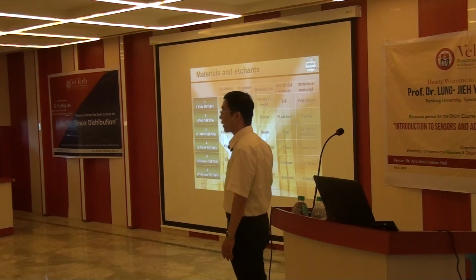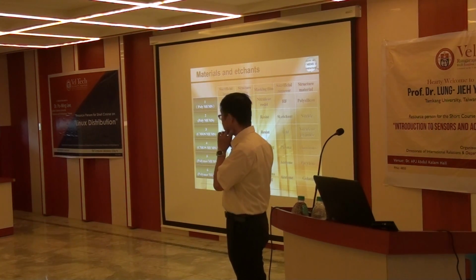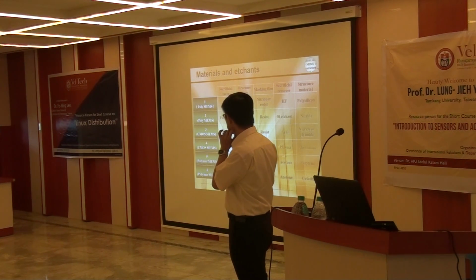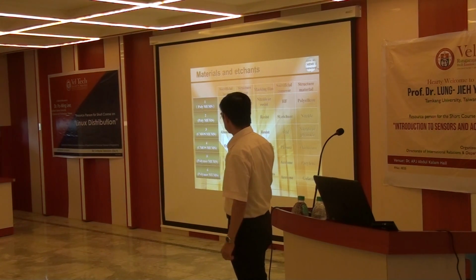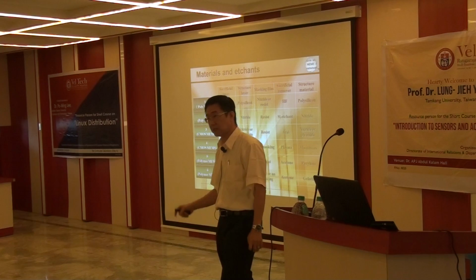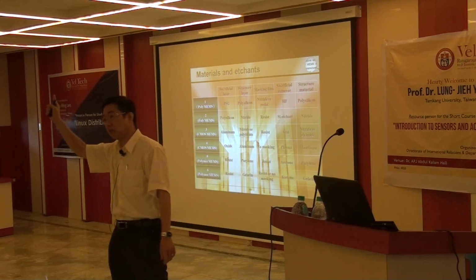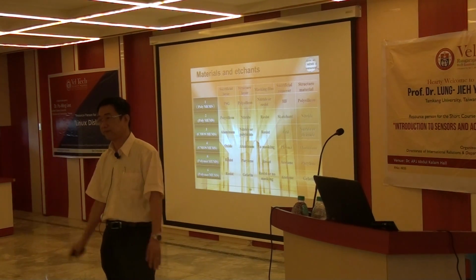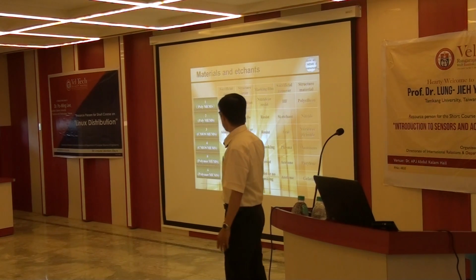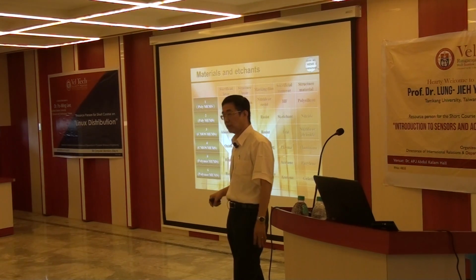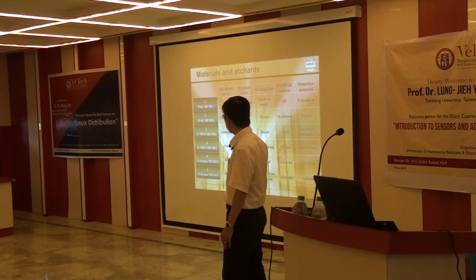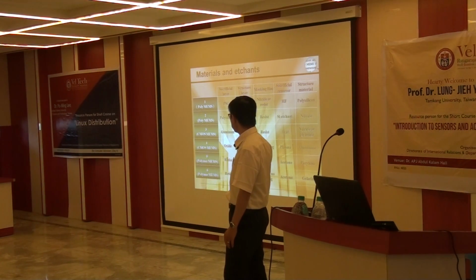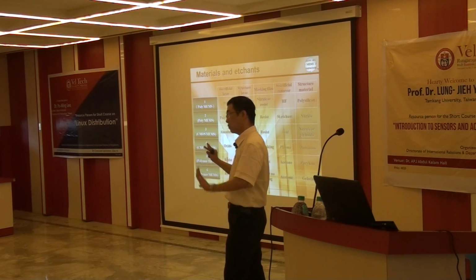Of course possible. We use LPCVD to do the coating. Polysilicon temperature is about 600, it's still fine. Glass can endure temperature up to 1000, no problem. The growth of the polysilicon is only 600 degrees C, so safe for glass. So coating the sacrificial layer PSG first, and then polysilicon second, no problem.